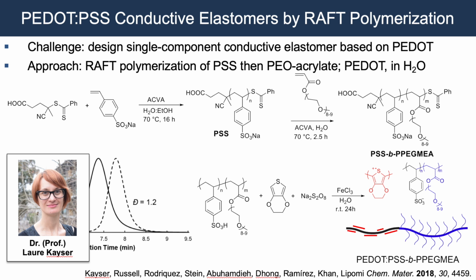So our goal here was to make a more compliant material. We co-polymerized this PSS segment with this segment, which is kind of like a bottle brush. This is polyethylene glycol, which is very well hydrated. We had the idea, or the hope, that it would decrease the contact impedance with the skin.